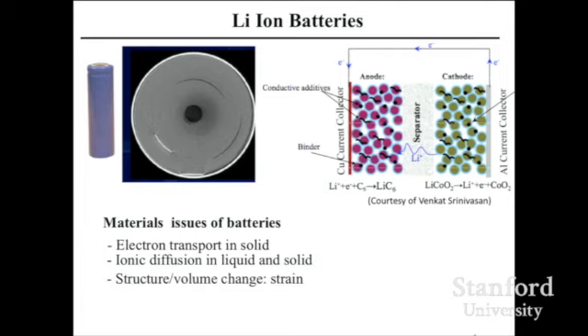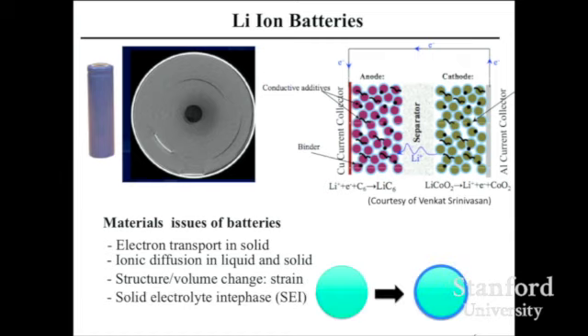You need the structure and volume to be stable. If this moving of lithium back and forth creates structural changes, that's not good either. And then there's the so-called solid electrolyte interphase. On each of these particles, the reaction with the organic electrolyte produces a passivation layer. You want this layer to be stable. If it is not stable, you keep consuming electrolyte, and the battery also dies very fast. So these four things need to work together very nicely in order to have a nice battery.